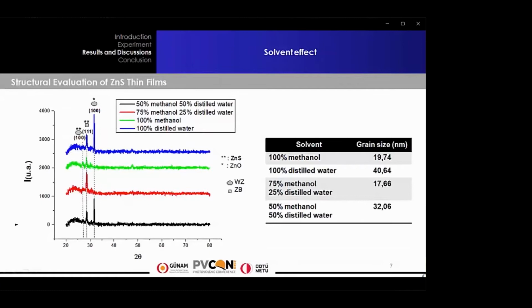In this study, we present the results for different solvents with a substrate temperature set at 415 degrees Celsius. The figure shows the X-ray diffraction profile of ZnS thin films grown in different solvents. ZnS is known to have zinc blende and wurtzite structures. The peaks of zinc blende ZnS were observed for samples grown in different solvents, and a wurtzite ZnS peak was observed in samples grown in 100% methanol solvent.